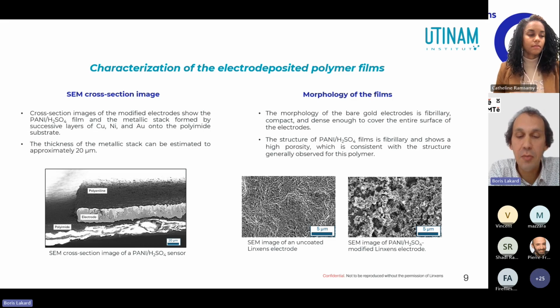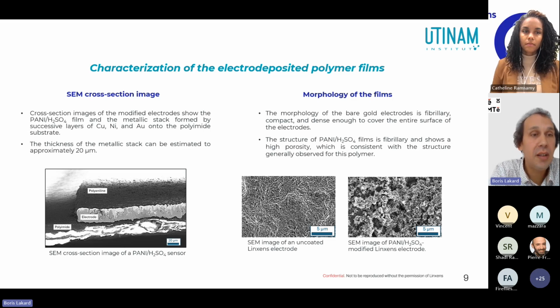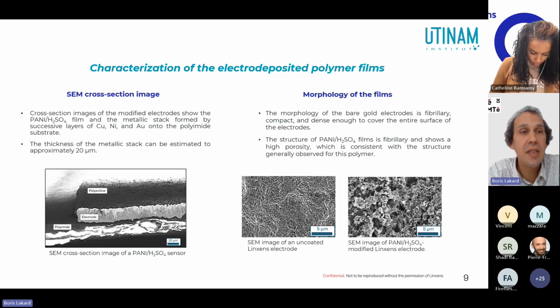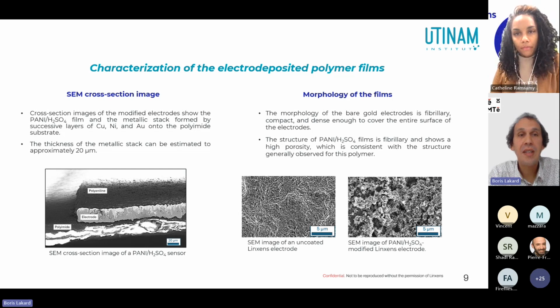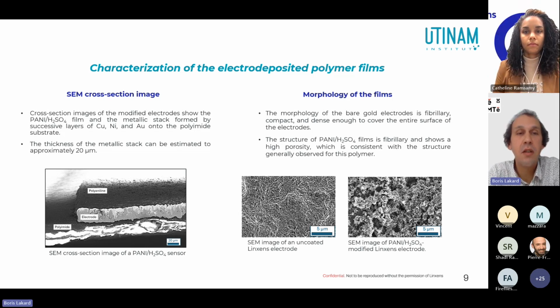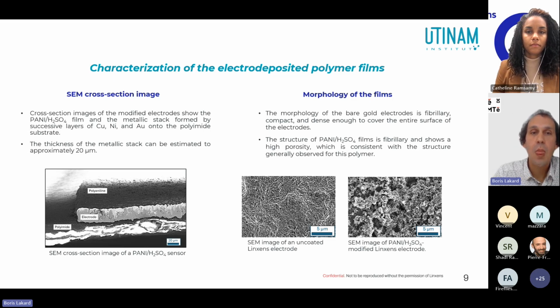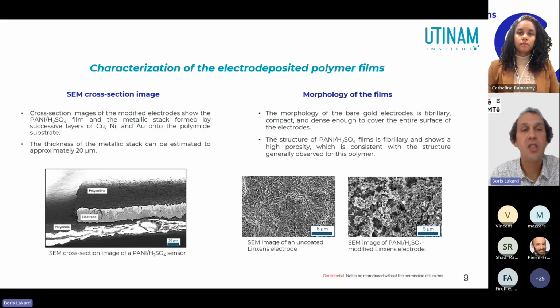We then characterized the electrodeposited polymer film using electron microscopy. On the left, you can see the cross-sectional image of the prepared sensor. This image shows the polyimide substrate below, the Linxens metal electrode, and then the electrodeposited polymer film. On the right, you can see the morphology of the deposited gold, which is very compact and granular. You can also see the morphology of the polymer film, which is spongy. So you have a strong difference of morphology between the polymer and the initial electrode.